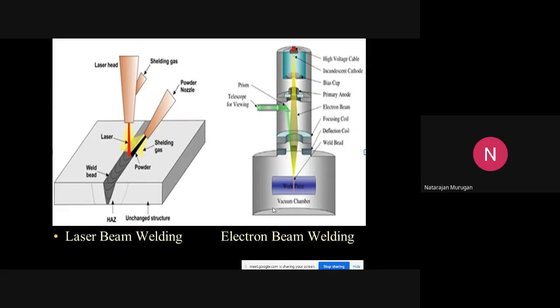Okay, the laser beam diameter is 0.1 to 2 mm. We used laser beam welding available at WRI, Welding Research Institute, for joining a 304 stainless steel plate of thickness 3.5 mm. We used a 4 kilowatt laser. The beam diameter we used is 0.6 to 0.8 mm. So you see, we melt just the edges and you can join. Sometimes we cannot see any heat affected zone. So there is less heat, less distortion, less residual stress, and a lot of advantages, but the only drawback is that the cost is very high.